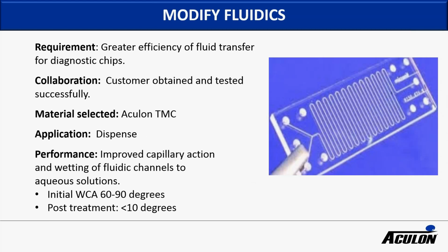Another area where hydrophilic treatments seem to be quite important is for polymers, where you're trying to get aqueous solutions to wet and have good fluidic properties. Here we essentially used the hydrophilic TMC. We dispensed it into the polymer. It takes the water contact angles from an initial 60 to 90 degrees down to less than 10 degrees, and really improves the capillary action and allows the wetting of the aqueous solutions throughout the fluidic channels.